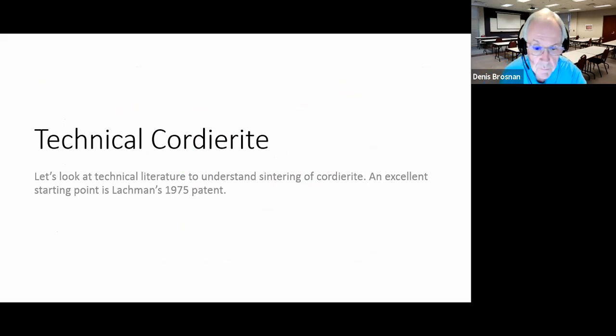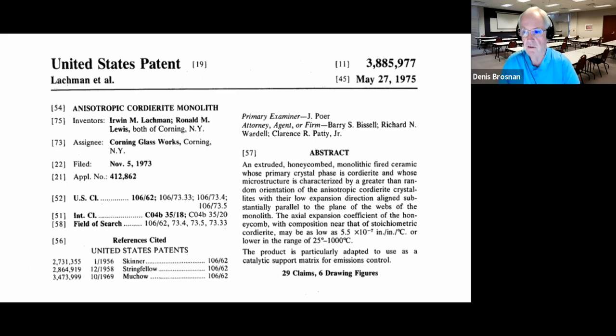Okay, well, let's look at technical cordierite. Understand what's out there in the literature, what we can glean from that. And I like to point you to Lachman's patent. Now, this is an old patent, 1975, but it is a wonderful patent. And so in this patent, Lachman says that he's talking about making extruded cordierite. You can have a thermal expansion coefficient as low as 5.5 times 10 to the minus 7. That's about 0.55 times 10 to the minus 6, in the range 25 to 1000 degrees Celsius.